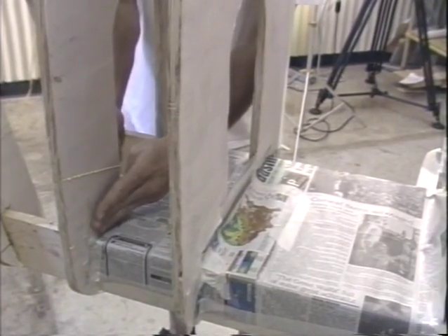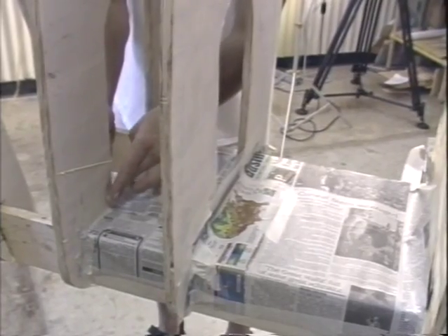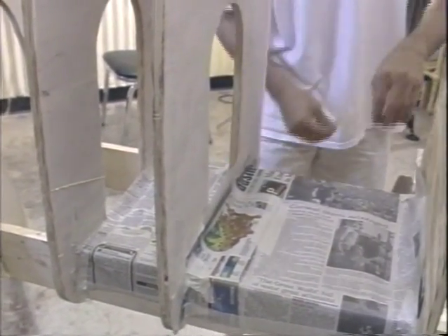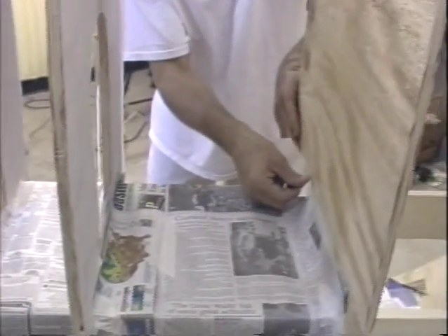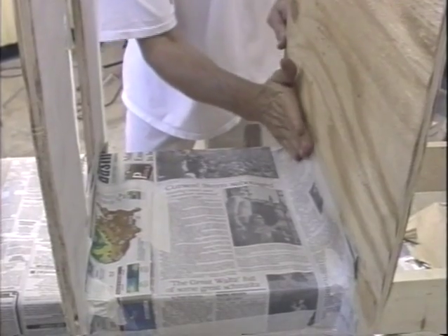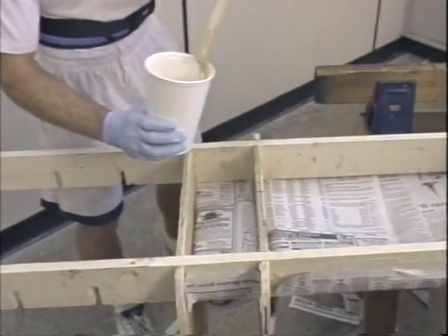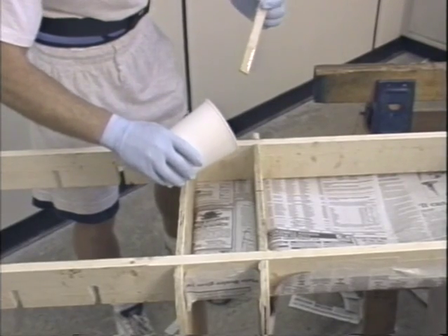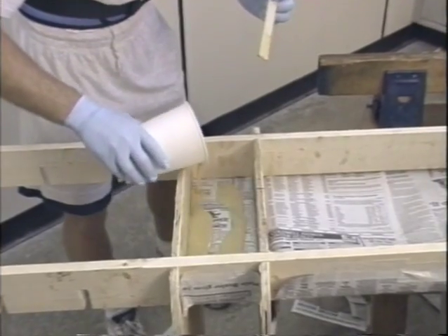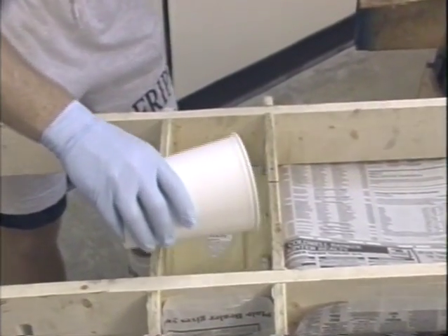To save on foam, we didn't fill the entire plug, just the surface perimeter. It was easy to tape newspaper to the bottom of the frame, creating loaf pan type cavities when the frame was flipped over. Pouring into these square cavities was straightforward, so we began there. You have to seal all the edges with tape to prevent the foam from draining out. The foam is a liquid which you pour into the cavity. It will expand to 30 times its volume in the liquid state. If the size of the cavity is known, divide that by 30 to determine the volume of foam to mix.